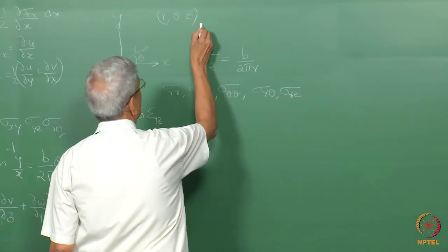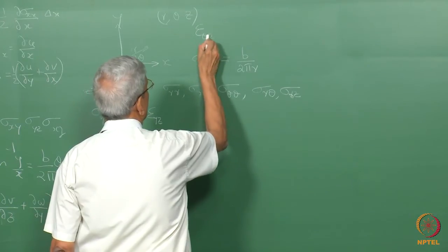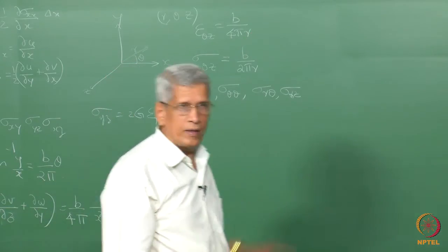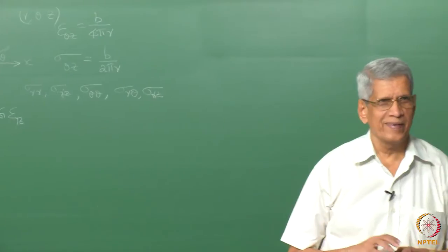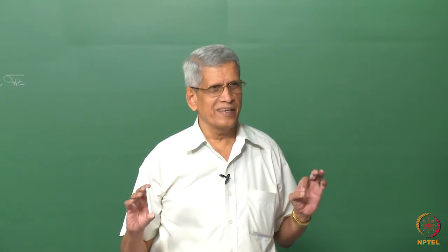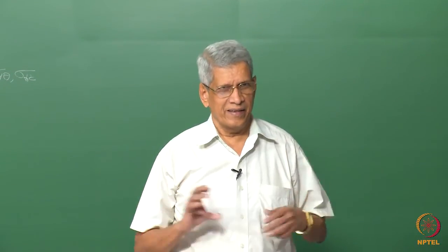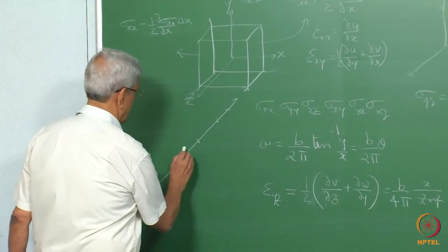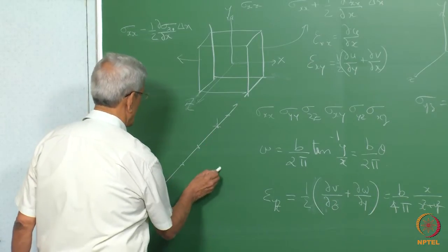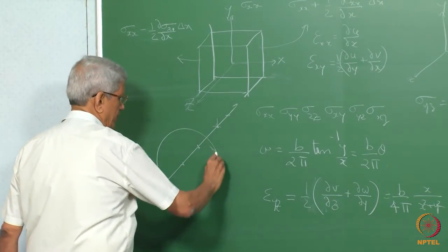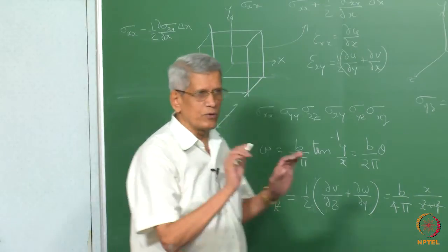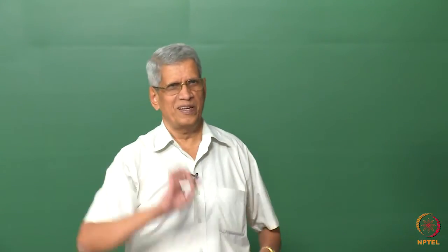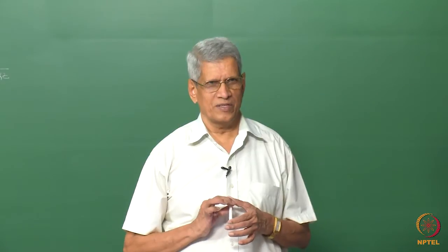From the cylindrical form, we can see that the stress field is essentially radial — around the dislocation line, the shear stress is the same at any point at radius r. On any circle around the dislocation, the same value of stress is obtained.